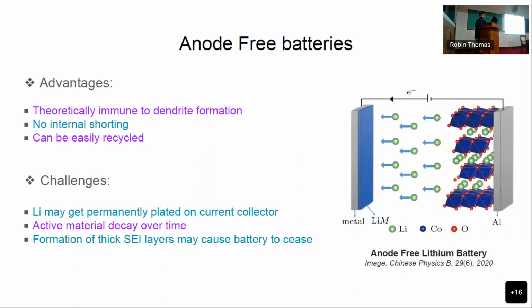So challenges are these, like lithium may get permanently plated on the current collector, and this will lead to less lithium available for the subsequent cycle, which decays the active material over time. And formation of thick SEI layers may cause the battery to cease. So the solid electrolyte interface still forms in this case because of the reactions, and if this layer grows thick enough, it won't be possible to get a proper cycling efficiency.